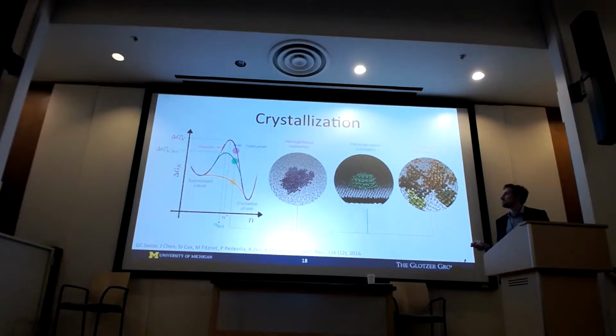We can use heterogeneous nucleation to make this a little easier. The surface is already here, but there's still a surface around it, so it makes it easier, but not completely free. And this is kind of the big problem. We need to overcome this large free energy barrier here to even start this nucleation process, and it still happens.